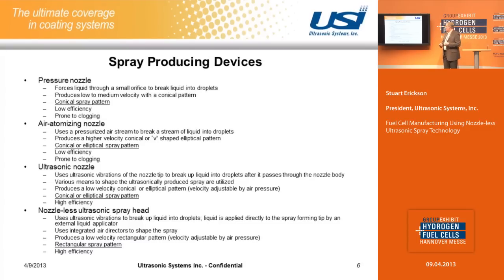So what we do with this technology is, since we don't use any type of a nozzle, we use a rectangular shaped spray device, we can produce a rectangular pattern. And that's very critical for applying a uniform coating on a flat substrate, which is the case for most fuel cell applications. Again, this is high efficiency technology, similar to an ultrasonic nozzle. They're both equal efficiency in terms of minimizing the bounce back.